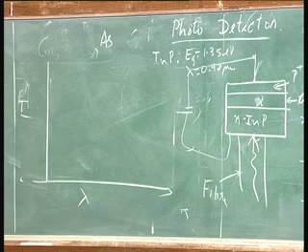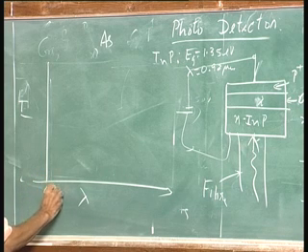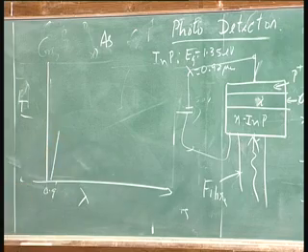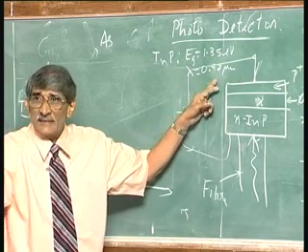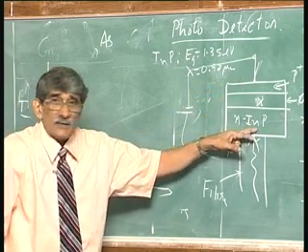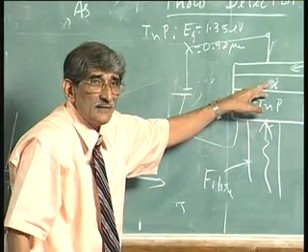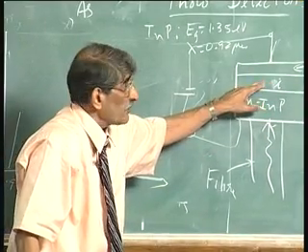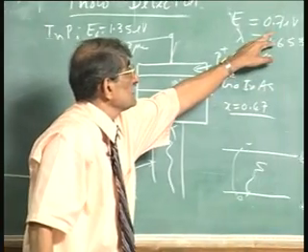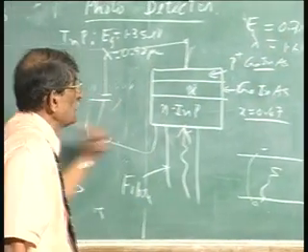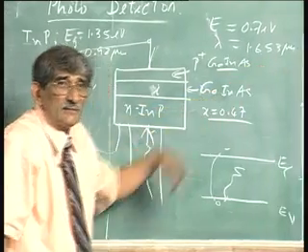When the wavelength is 0.9, up to that point nothing is absorbed. When the wavelength becomes more than that, this will not absorb, this will act as a window, it will fall on this. This will absorb whenever the energy is right up to 0.7. So, from 0.92 up to 1.6 microns, this layer will absorb.